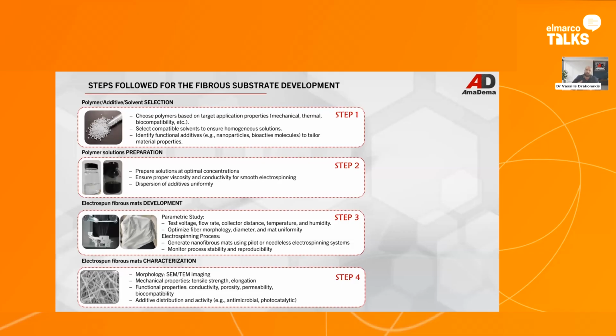And then after that, we have the normal electrospinning development process in order to find out the necessary parameters, depending again on the materials that we have selected above, and eventually do characterization with scanning electron microscopy mostly, mechanical properties such as in-plane tensile strength and elongation. We have a very sensitive head for the UTM for the mechanical testing, and the functional properties: conductivity, porosity, permeability, biocompatibility, and additive distribution.